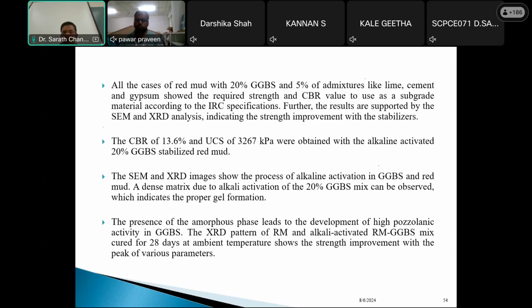So among all the combinations, we achieved the best CBR and UCS with alkaline activators, that is sodium hydroxide and sodium silicate. If you apply red mud directly with sodium hydroxide and sodium silicate, it will not work much. But when you mix with the GGBS or the fly ash, definitely it gives better values and a better strength. And 13.6% is absolutely fine. When I presented this in one of the international conferences, they appreciated that achieving more than 10% CBR is very good to use in road construction, where industries can accept.